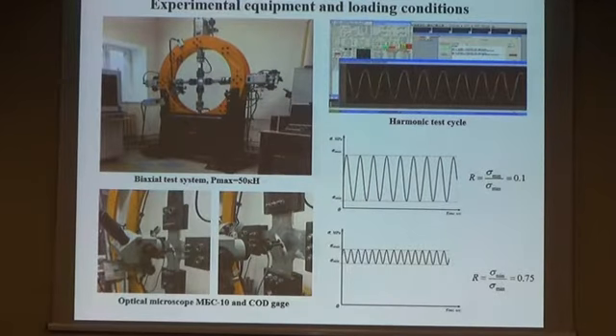The fatigue crack growth rate tests were carried out with servo-hydraulic biaxial test system at room temperature with sinusoidal loading form at frequency 5 Hz, and the stress ratio R equals 0.1. Both optical microscopy and crack opening displacement method were used to monitor the crack propagation during the test. And in order to fix and highlight the crack front positions as a function of accumulated numbers of cycles of loading, several benchmarks were produced by increasing the stress ratio from 0.1 to 0.75 with a constant value of maximum cyclic stresses.